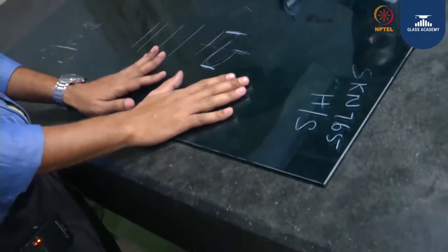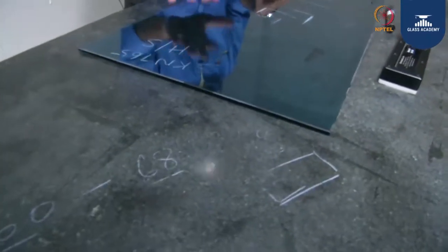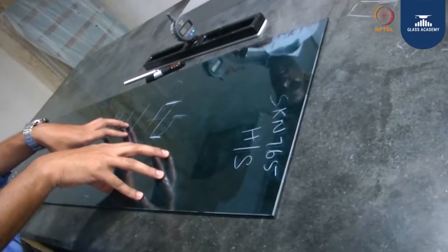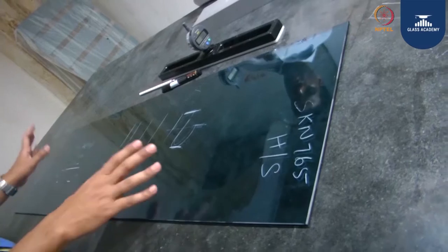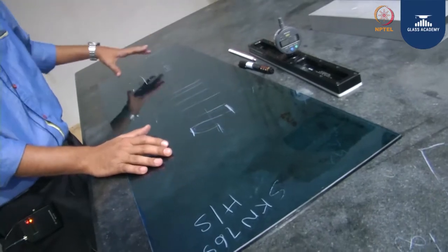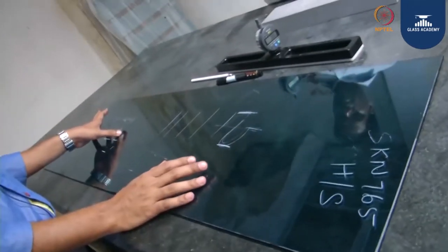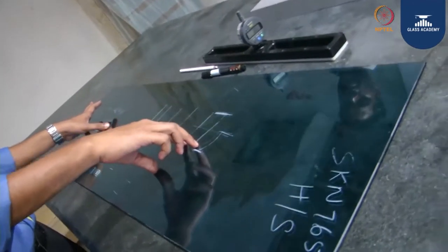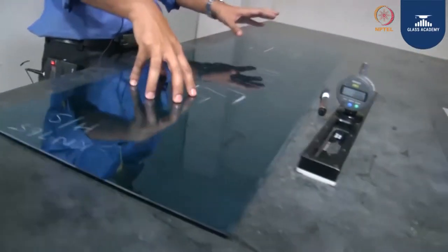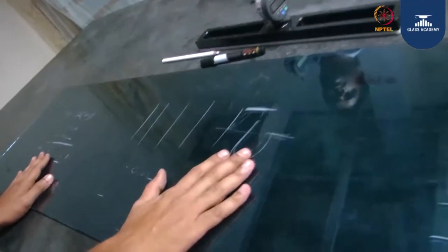Now, to recap, I'm just summarizing how we are going to measure the roller wave. First, we need to take a 1100 by 360 sample as per the standard EN1863. Next, we need to take a roller wave gauge. The placement of the roller wave gauge is to be perpendicular to the glass direction. Next, we need to leave 150 mm on the edges. Then we start dragging the roller wave gauge on the glass surface. We need to note down the maximum and minimum value. The summation of the maximum and minimum value will give the roller wave on the glass. The allowable roller wave as per the standard EN1863 is 0.3